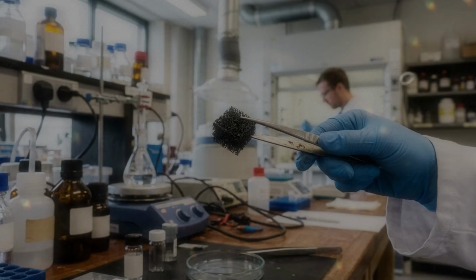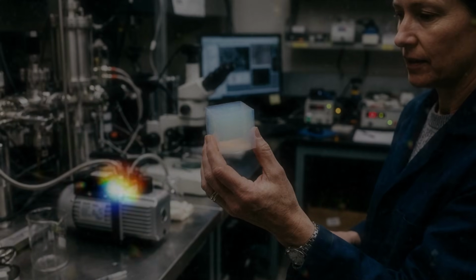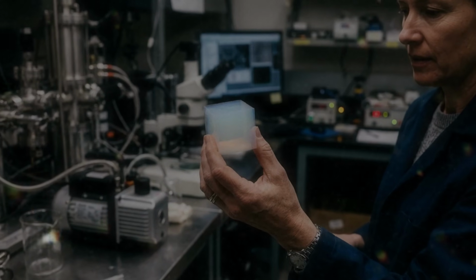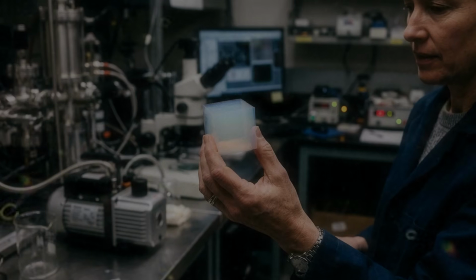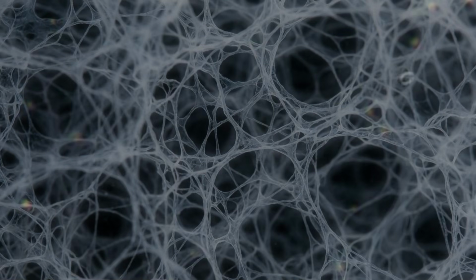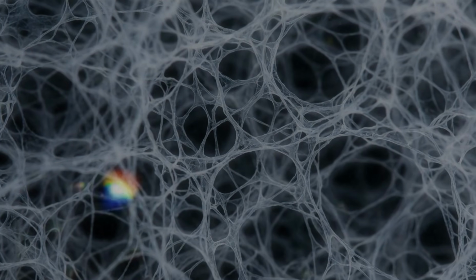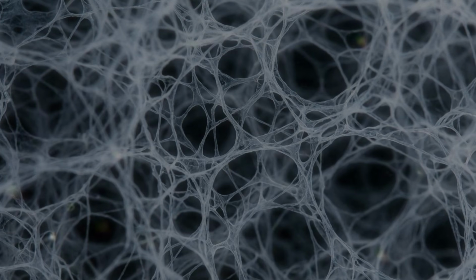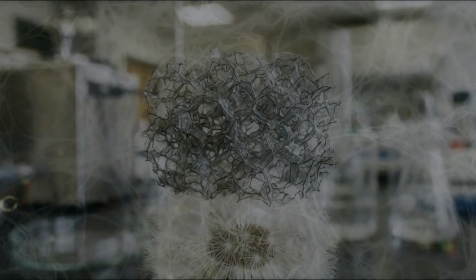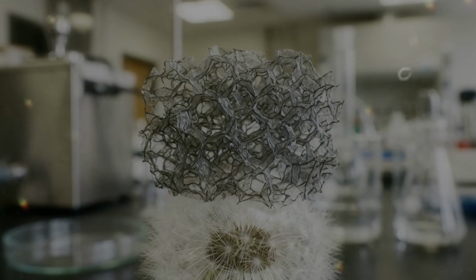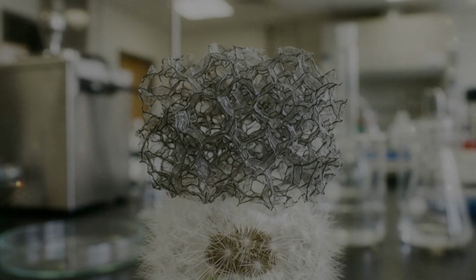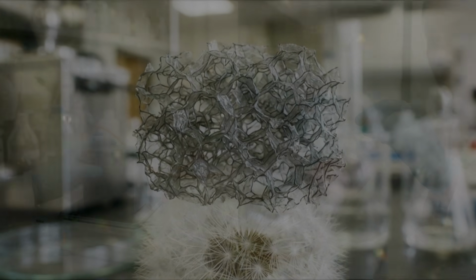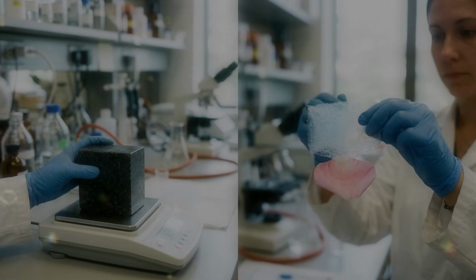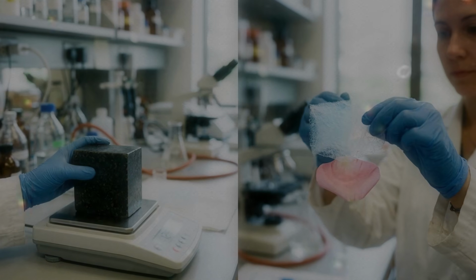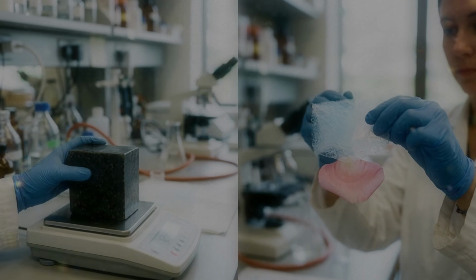Repeated movement causes fatigue. Tiny cracks form. Contacts wear or shift. Some sheets remain stuck together. The height may recover slightly less after each cycle. Good aerographene design reduces this damage. Strong junctions prevent sheets from pulling apart. Curved walls avoid sharp points where stress concentrates. Reinforcing fibers spread force. A regular cell pattern makes deformation more predictable.